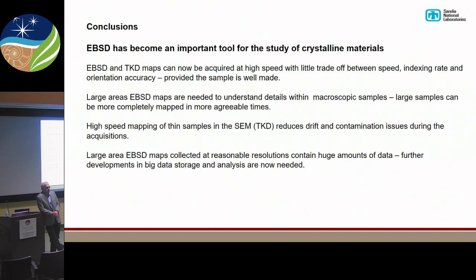Where the core might be rather large compared to maybe in a ceramic or something like that. But in metals, they're certainly starting to push the science that way and doing strain analysis around dislocation cores. So there is some work in that area. It's new, past 2 years or so. So it's just brand new stuff. But they do a cross correlation, so they actually need a pattern from undistorted material. And then they do cross correlation all around for every pattern they collect. And they can do subpixel shifts and subpixel strains and actually calculate the elastic strains around features in a microstructure.